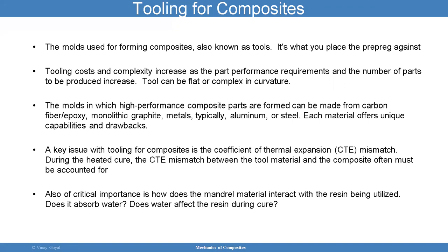While that may not be the case for other applications, a key issue with tooling for composites is the coefficient of thermal expansion mismatch. That's what I just discussed. And so going with high performance applications, you can minimize those issues. When you're going through a heating cure, the CTE mismatch between the tool material and the composite has to be accounted for in the dimensional tolerancing, and also the quality that you get at the end, because you may have some residual stresses.